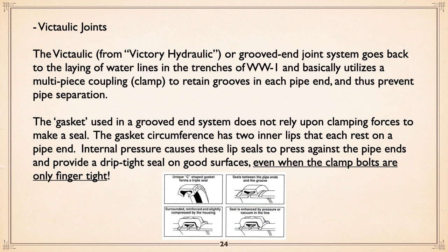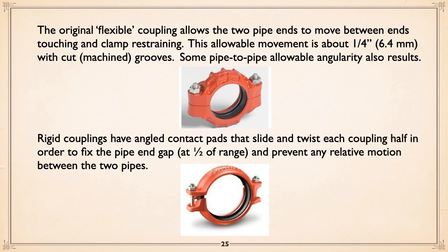We got into it at one time because we're doing package stations and booster units, whatever, and you bolt it together with flanges. And by the time it got to site, the first thing you did is spend an hour to tighten up all the bolts because they loosened. With grooved end, no. It'll test drip tight, and after being shipped, it will be drip tight. And the clamp bolts don't have to be super tight. Say even finger tight. Well, you want a little tighter so they don't just magically fall off, but that's not what's making the seal.